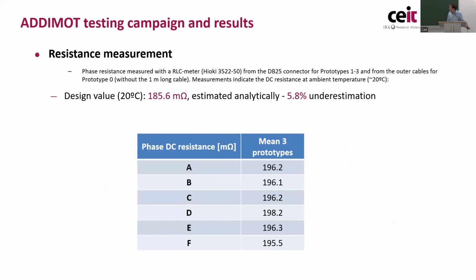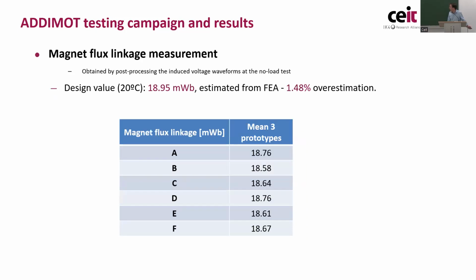Then we proceed to normal tests, resistance measurements. Quite good estimated by the design. It's only a 5.8% underestimation of the resistance values of every phase. It's a 6-phase motor.